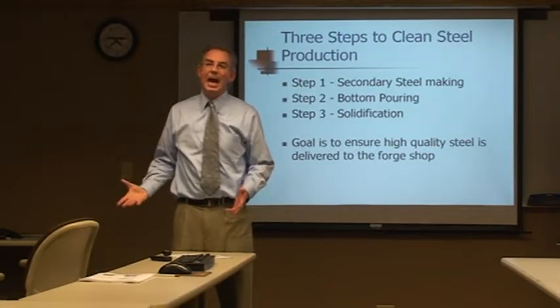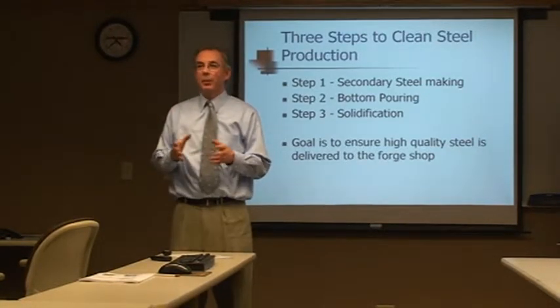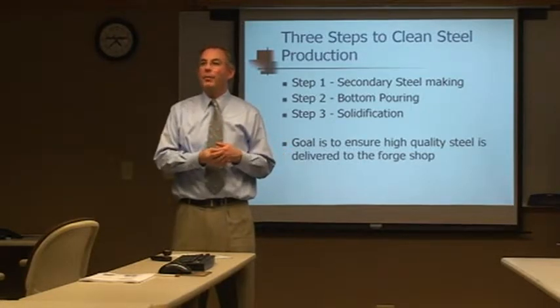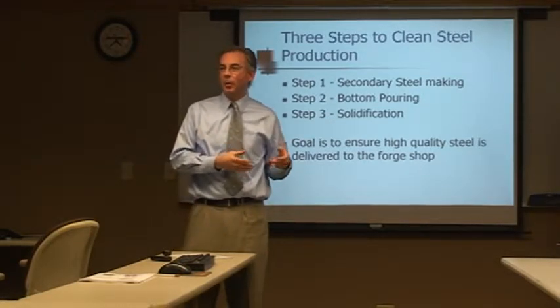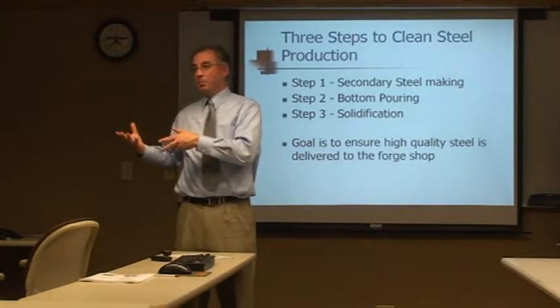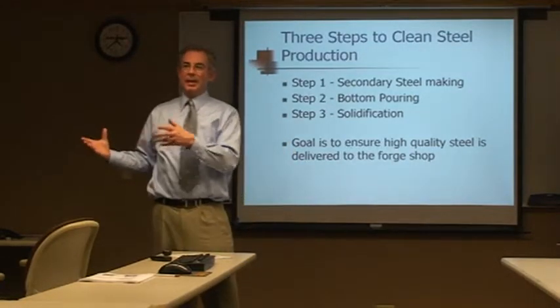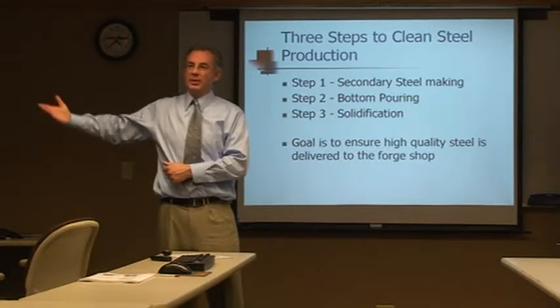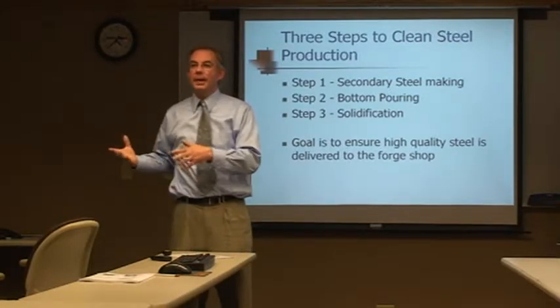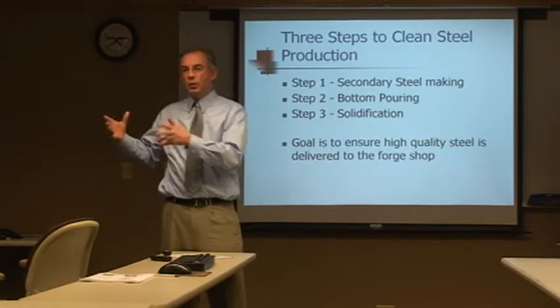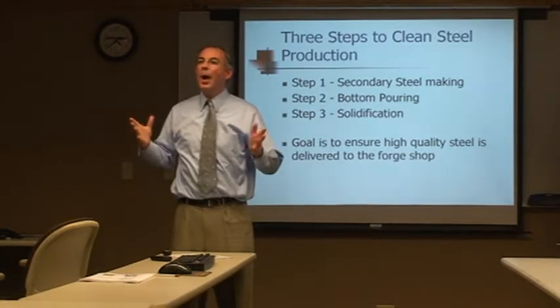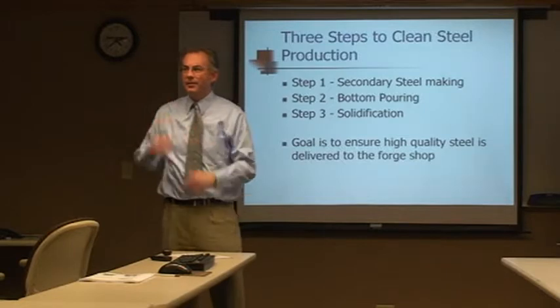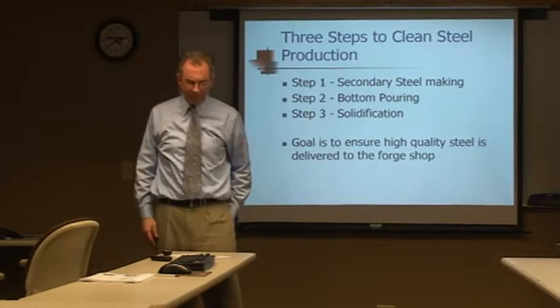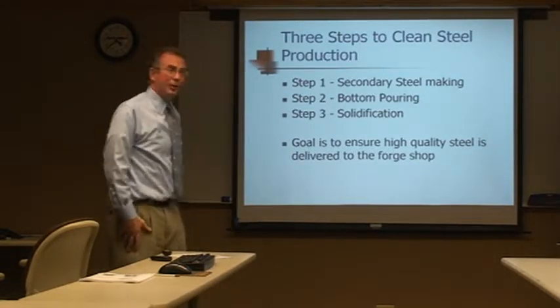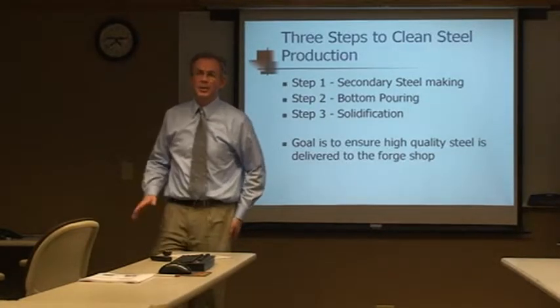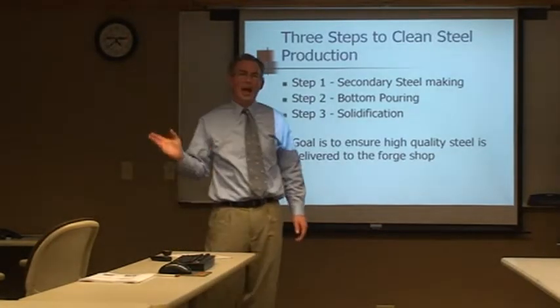Our mold sizes, touching base on it real quick, come in a wide variety. A 10-inch diameter would be our smallest mold, and we make all the way up to 60 by 79 cross section. Most recently, we've just added an 82-inch diameter mold, which is actually a 2-heat pour. It's a pretty wide variety, about 50 to 56 different mold sizes. We're going to circle back to what Dan just gave us, a really good overview of what's happening through it.